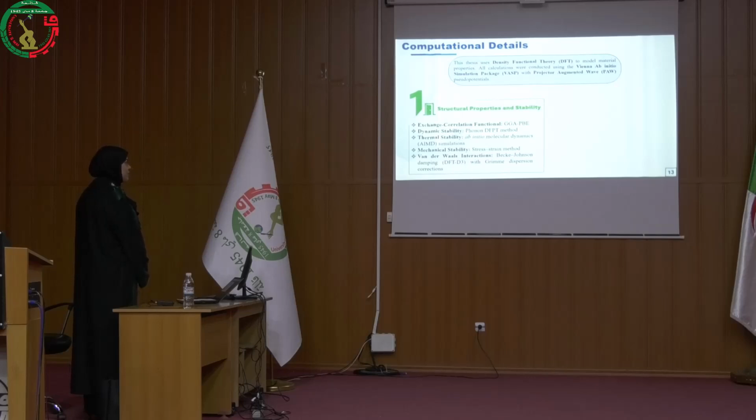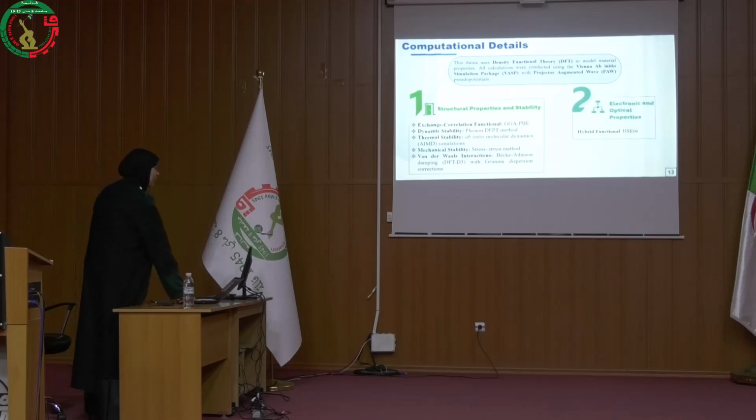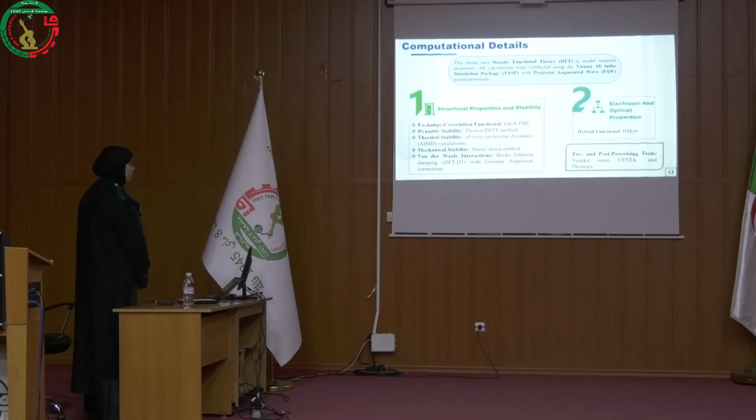The dynamic stability was determined through phonon calculation using the density functional perturbation theory method. Thermal stability was assessed via ab initio molecular dynamics simulation. Mechanical stability was determined using the strain-stress method. The van der Waals interaction was treated using Becke-Johnson damping DFT-D3 with Grimme dispersion correction. Electronic and optical properties were calculated using the hybrid functional HSE06 to accurately predict the band gap and optical properties. For pre- and post-processing, VASPKIT, Sumo, VESTA, and Phonopy were utilized.